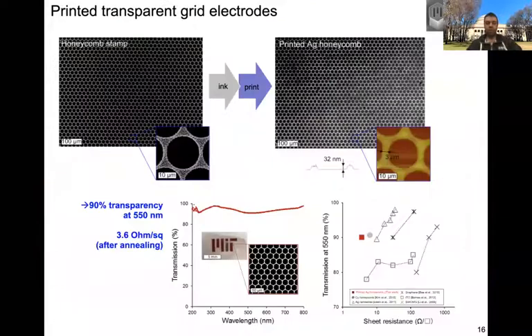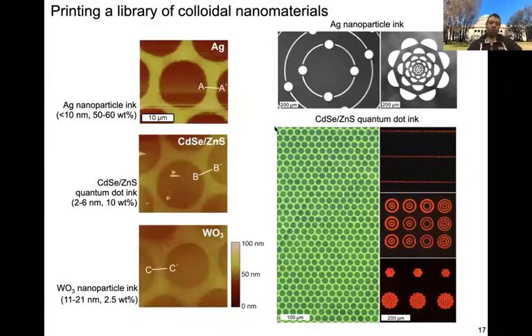So we can do things like print honeycomb type transparent electrodes, where you have a lot of open area, but you have solid area that's metal, and get good combinations of transmission and low sheet resistance over a visible wavelength range, and also apply this process to printing a variety of different colloidal inks.